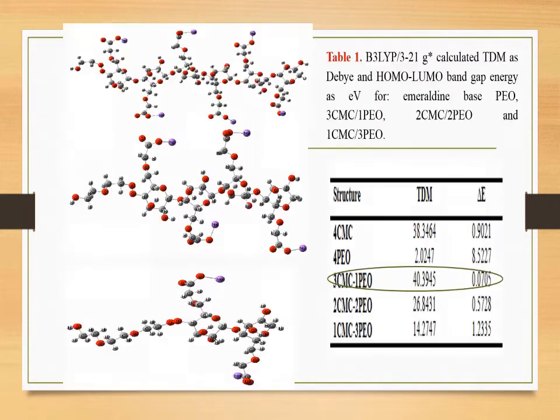Results and discussion. This figure shows the three mechanisms of interaction between CMC and PEO, which are trimer CMC with monomer PEO, dimer CMC with dimer PEO, and monomer CMC with trimer PEO. Here the effect of blending was discussed in terms of total dipole moment and HOMO-LUMO band gap energy in electron volts. As we know, blending of polymeric materials provides enhancement in the electronic properties of the individual polymers that is helpful for electronic applications. As we see from the table, the total dipole moment values changed and the HOMO-LUMO band gap energy decreased as a result of blending CMC with PEO.